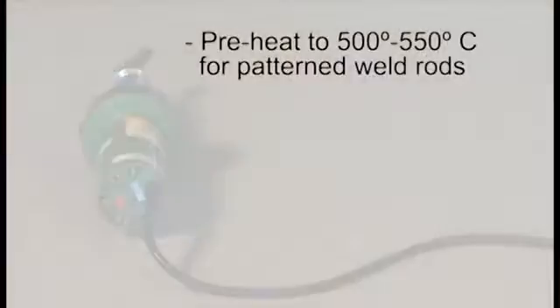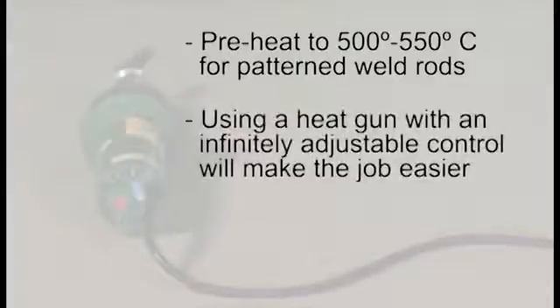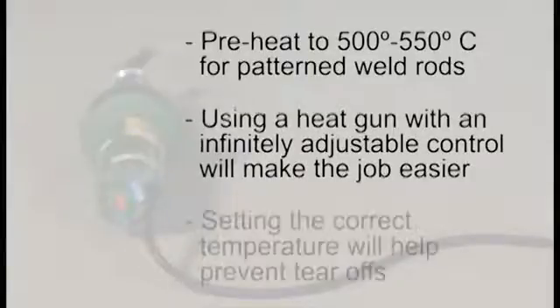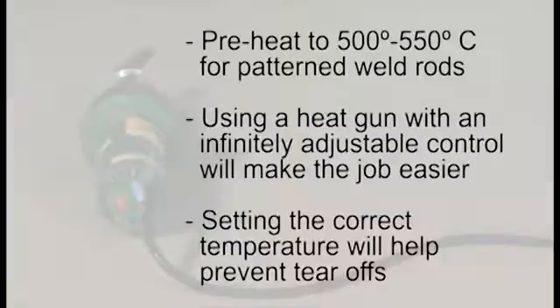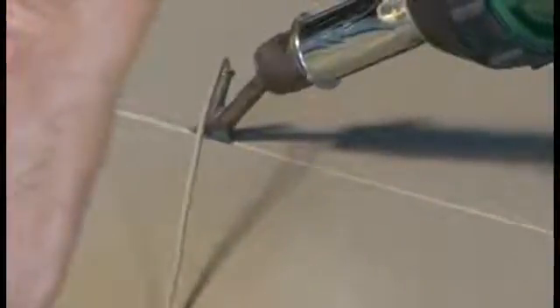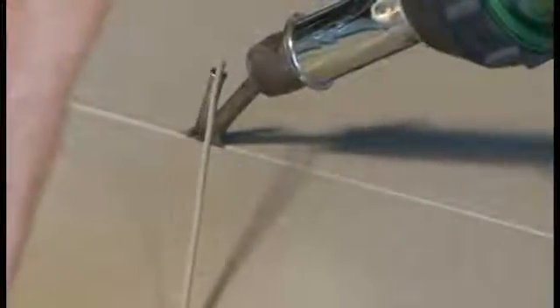When using pattern weld rod, the heat gun temperature will need to be set slightly higher than the temperature normally used for solid colored welding rod. This temperature is approximately 500 to 550 degrees centigrade. A heat gun with an infinitely adjustable temperature control will make the job easier. This will also help to prevent tear-offs. Practice on a piece of scrap material with the correct nozzle to determine the correct setting and welding speed.